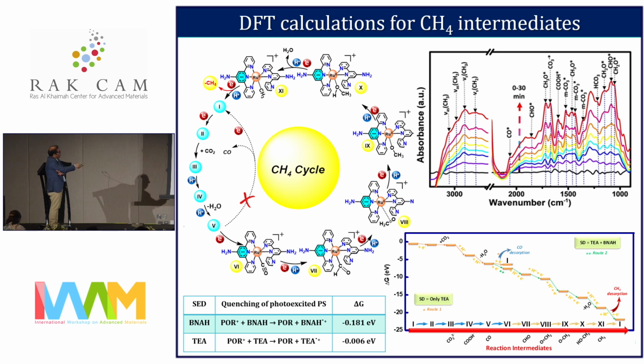This means the process slowly shifts - in the presence of BNAH, the delta G zero value is much lower compared to before. This process goes to an 8-electron reduction process, which is much more favorable based on the free energy diagram. So we were able to do this by changing the light harvesting process, particularly by changing the electron donor from triethylamine to BNAH - you can retune the product selectivity from 2-electron reduction to 8-electron reduction.